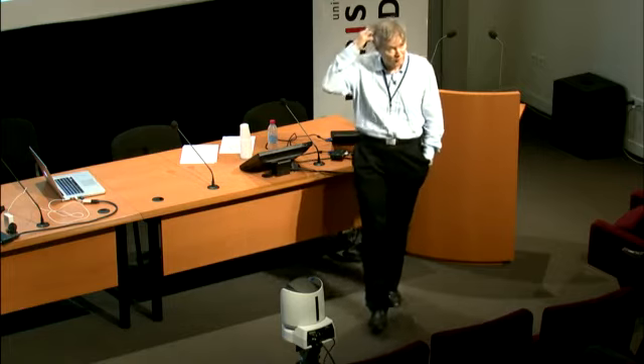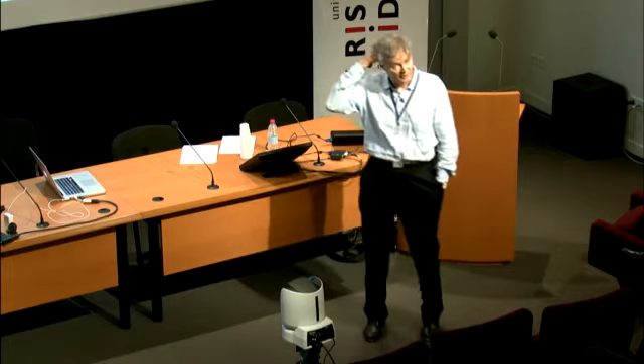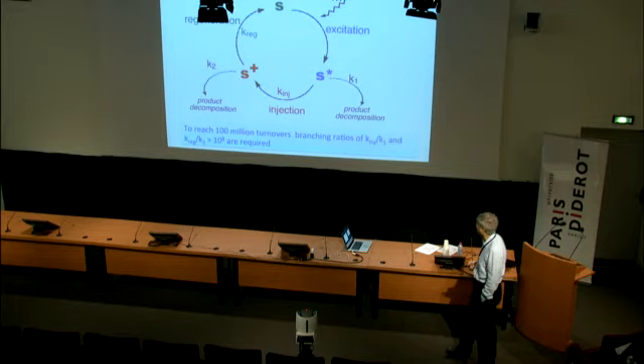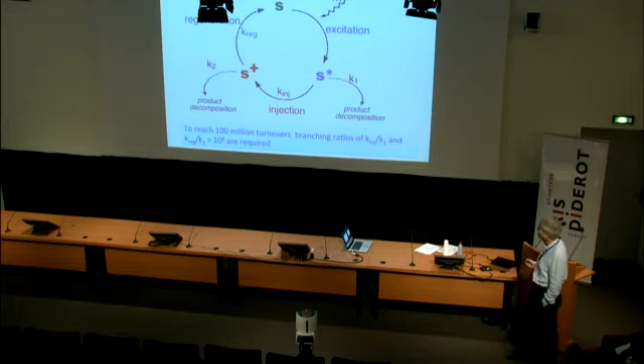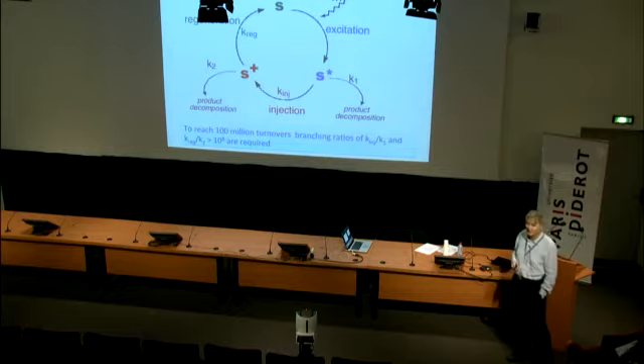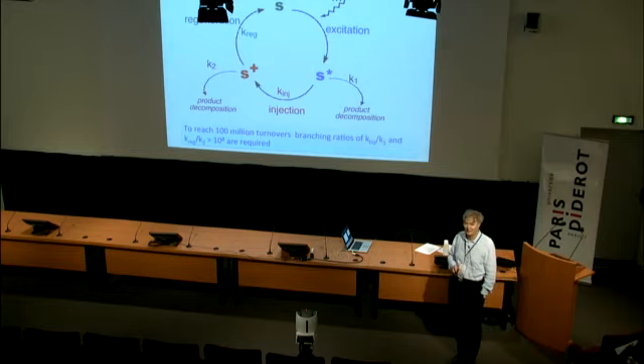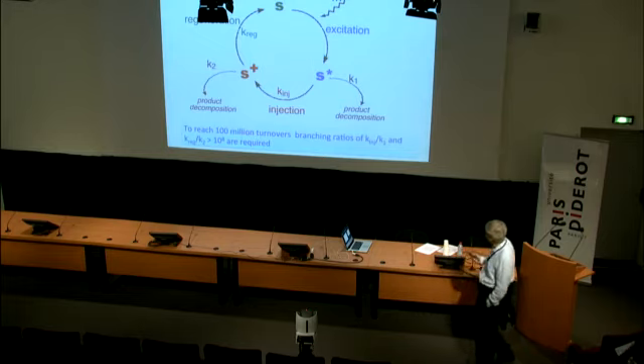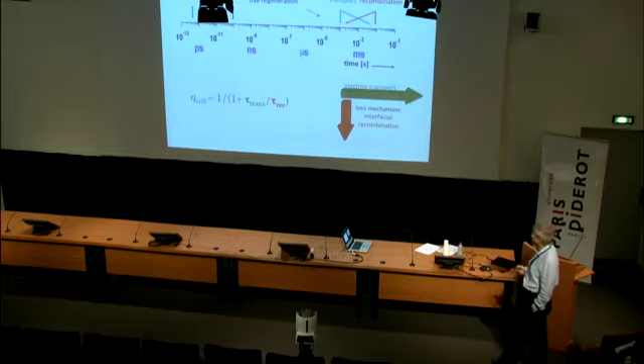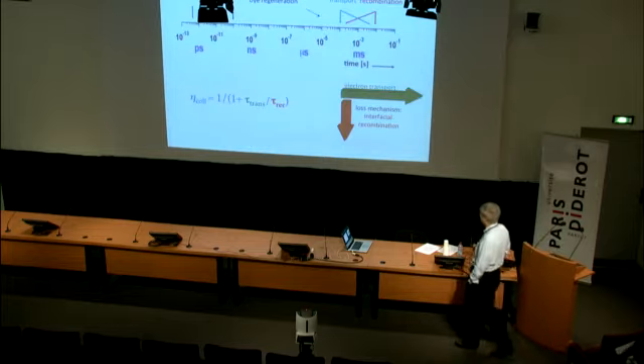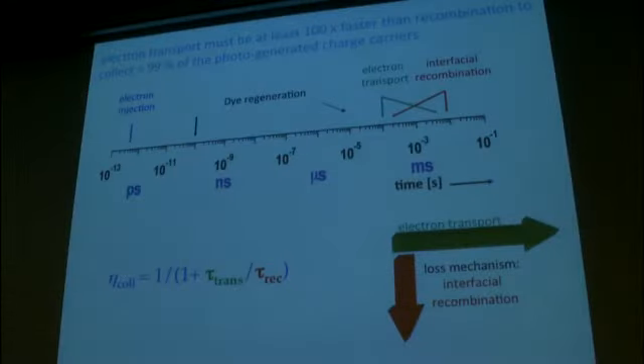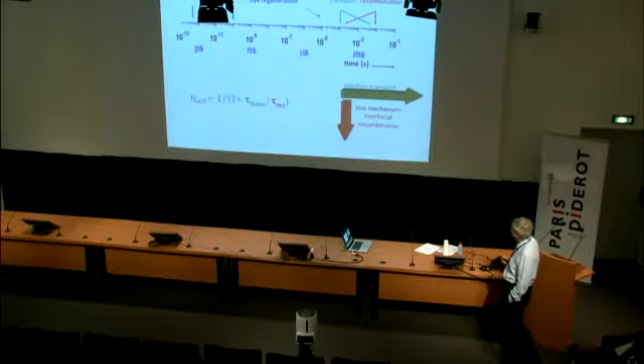But very long-term experiments have been performed. The longest one, 4 or 5 years, full artificial sunlight on the cell, with very good stability for the sensitizer. So it's not all, but the sensitizers which are selected for these cells are selected such that they fulfill these kinetic requirements. Now just to wrap up this initial part of my talk, collection efficiency is very important. I mentioned that to you. So very fast electron injection, then the regeneration. This is femtoseconds. This is nano to microsecond. Electron transport and interfacial recombination.